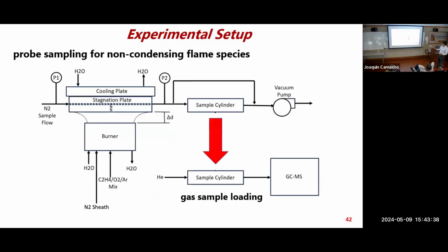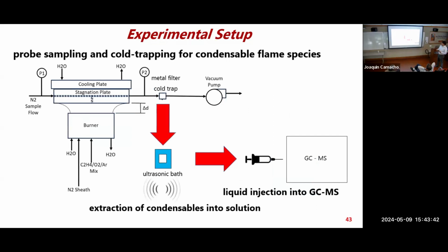And then when we have a liquid solution of sample, we can inject it into the analyzer. So this is two methods. One just for gas phase, anything that stays readily in the gas phase, and the other for larger molecules that condense at room temperature. We use that condensation to collect them over time, and then hopefully extract them into solution and inject the liquid solution.